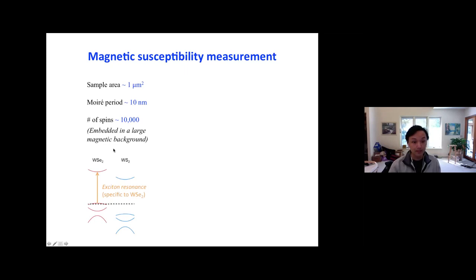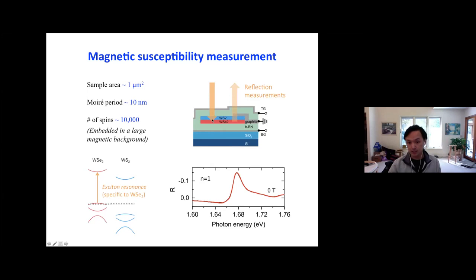So the way we do it is to resonantly enhance the detection method, so that we can pick out the response of the WSe2 by looking at a particular optical transition in the WSe2, this excitonic resonance corresponding to this vertical transition here, specific to WSe2. That would help us almost totally eliminate the big background of the substrate and other things. Well, it's a simple measurement. Basically, you shine light onto the system and you look at the reflected light intensity as a function of the wavelength or the photon energy of the system.